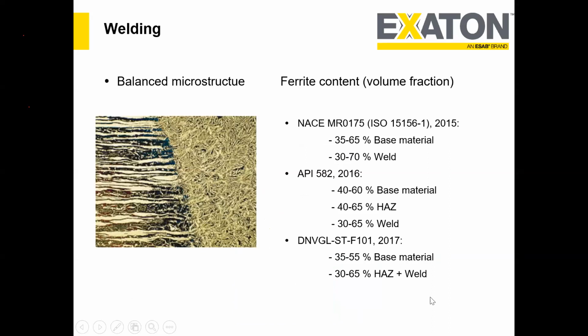I took some references from codes like NACE, API 582 and DNV. You see here, NACE puts the base material at 35 to 65%, and the weld metal from 30 to 70%. API 582 says between 40 to 60% for the base material, 40 to 65% for the heat affected zone, and for the weld metal 30 to 65%. DNVGL says 35 to 55% for the base material, and for the HAZ and weld metal 30 to 65%.